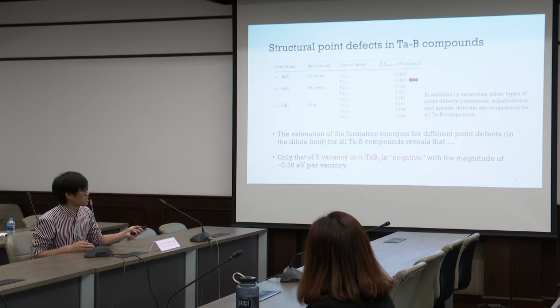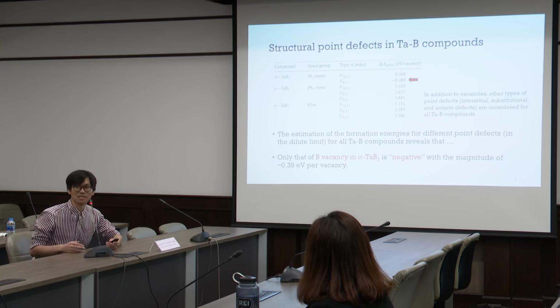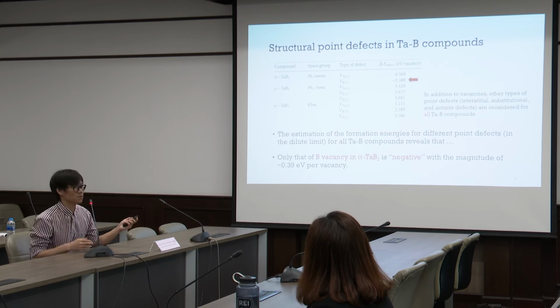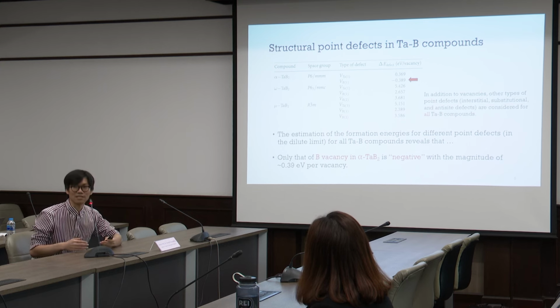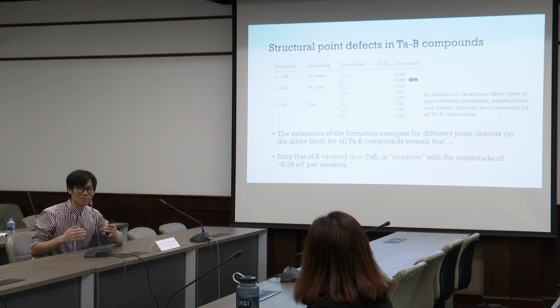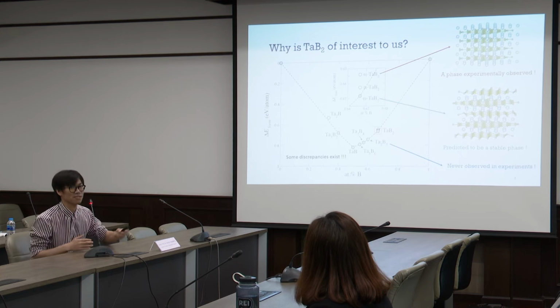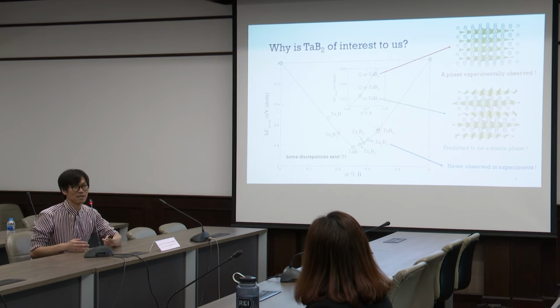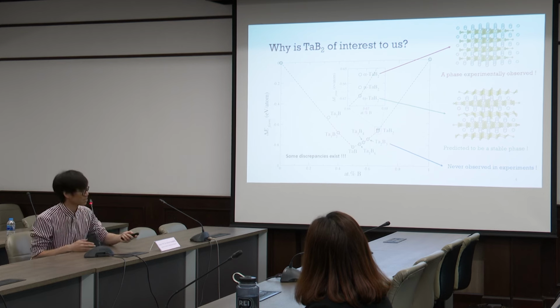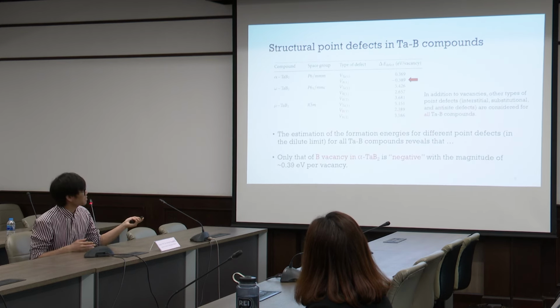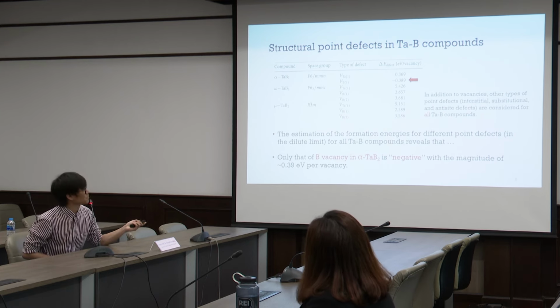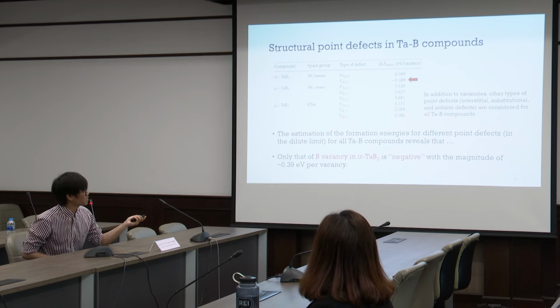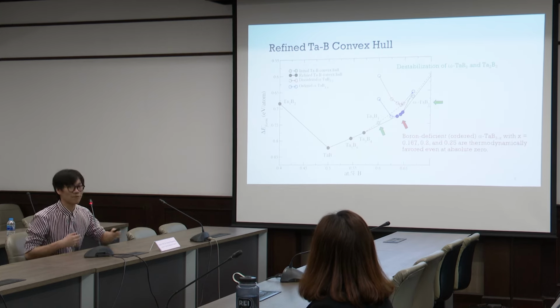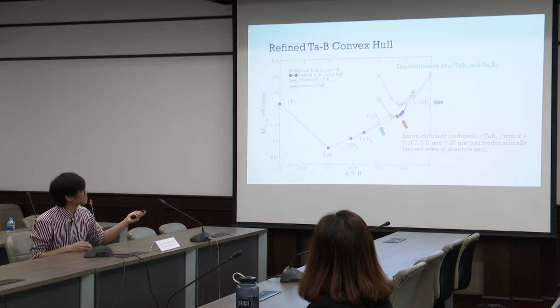What we did is consider that some defects might play a role in this discrepancy. So in this work, I studied several types of defects in this Ta-B compound, such as the tantalum vacancy, boron vacancy, interstitial defect, or anti-site defect. But the only defect that exhibits a negative formation energy is the boron vacancy in the alpha phase of TaB2. So I take this kind of defect into account in the modeling, and I refine the ground state line of this tantalum boron system.